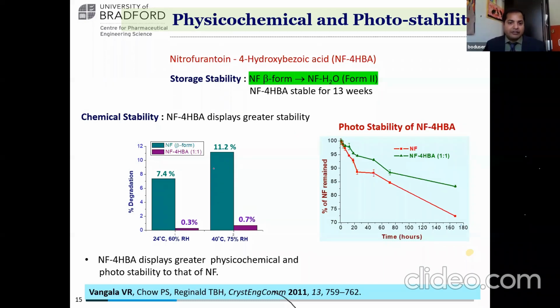Since we have a co-crystal, we studied accelerated and also room temperature storage. We exposed the materials, both nitrofurantoin itself and also nitrofurantoin 4-hydroxybenzoic acid, to the relative humidity and temperature conditions that I mentioned here. What we found was that nitrofurantoin was converting in the first test to the extent of 7.4%, that is, it converted into the monohydrate, and in the other case to 11.2%, whereas the co-crystal has almost no change. This is a very good sign. So co-crystals are offering physicochemical stability.